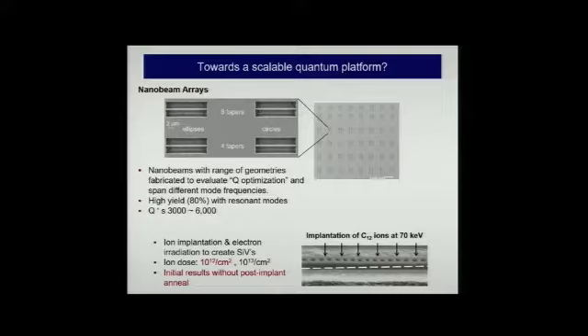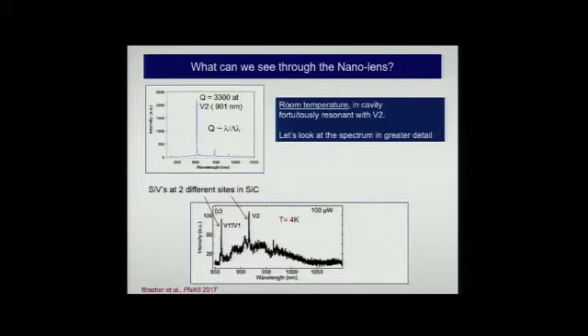I want to mention at this point that we've made the devices. We've deliberately introduced defects. We haven't, and we won't, anneal these devices until later. And for those of you who work with traditional devices, not annealing the device and not trying to remove the residual damage and expecting to see anything decent is actually a bit of hubris. But you'll see what we're going to see. So, again, just by placing the defect within the cavity, we bring exquisite signal out of noise.